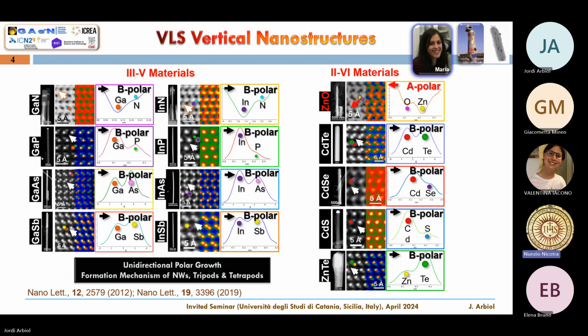And the same was happening here, like tellurium, selenium, and sulfur, and for many different types of materials. And this was what we called directional or unidirectional polar growth. So if you think about that, these nanowires were following a kind of growth conditions which were giving, let's say, the fastest growth. So whenever you wanted to grow these nanowires really fast, without defects, etc., you were obtaining these polarities. If you wanted to reverse the polarity, then you had to change the growth conditions a lot, and then the growth was really slow.